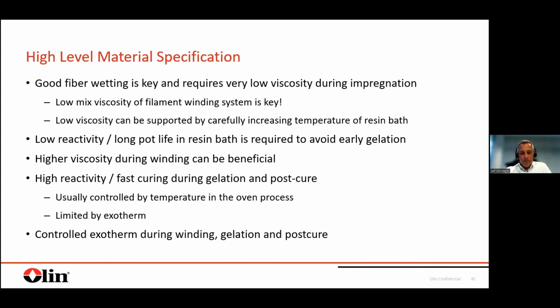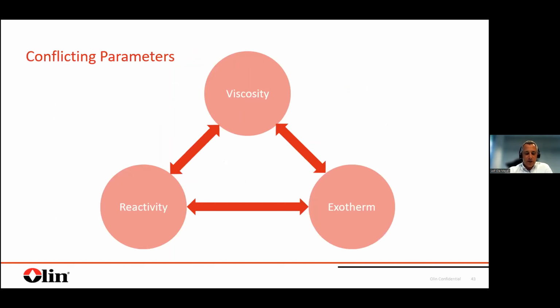So overall, it's coming back a little bit to a picture that I've been showing in the beginning with the balance. We have some conflicting parameters, and this is reactivity, viscosity, and exotherm. So regarding viscosity, you want to have it low, but you want to see a fast increase without exotherm. So this is chemically and physically a conflict in itself. Regarding exotherm, you want to see a low exotherm, but at the same time, you want to have a fast cure speed, which is again kind of a chemical and physical limitation that we have here.